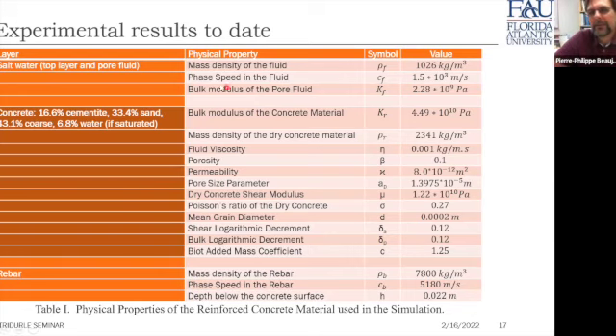So the parameters we actually use for the saltwater are the mass density, phase speed, and bulk modulus. For the concrete, we assume that we have a 16.6% cementite, 33.4% sand, 43.1% coarse, and 6.8% water mix, under the assumption that the sample is saturated with fluid, and we're talking about salt water here. Now, the bulk modulus of the concrete material, the mass density of the dry concrete material, the fluid viscosity, the porosity, and the permeability parameters are used to model the concrete.